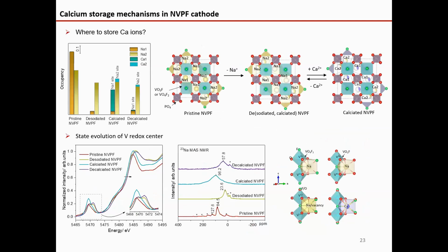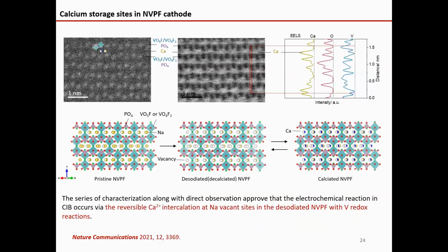And we also tried to understand where the calcium ion is inserted. By the calculation, we found that most of the calcium ions are inserted in the vacancy which we create by extracting the sodium ion. Well, normally we say seeing is believing, or in Chinese we say 眼见为实. So we also conducted the CS STEM. By the high resolution image, you can directly observe where the calcium ions are inserted in the host.